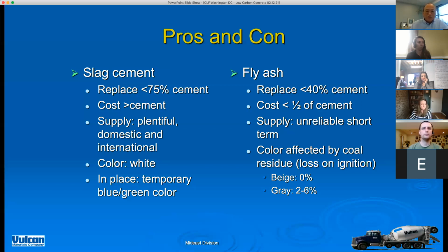The color of fly ash, if it's treated, beneficiated is the term that we use, removes the residual coal, and the measurement of residual coal is through loss on ignition. If it's 0%, the color is actually beige or buff color. It's a very interesting color. But if you have some amount of LOI, generally in the 2 to 6%, it can range from a very light gray to a very dark gray. So that's the color of fly ash.